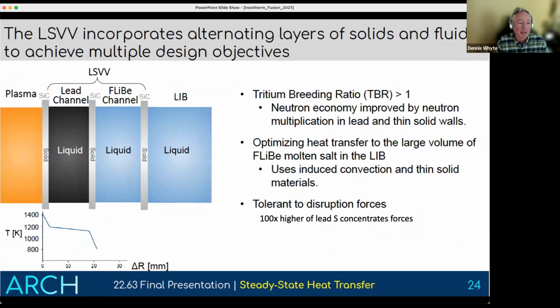So what was this idea, this liquid sandwich vacuum vessel? I'm not showing this that we proved it works, but it's an indication of the innovations, I think, which are needed in heat transfer. So if we think about this cartoon of the vacuum vessel, it basically needs to have a structural material solely to provide vacuum integrity. So what we did was try to eliminate even more solids out of the material, with the idea that we'd have thin structure silicon carbide solid structures, and then we'd have interleaved liquid layers.